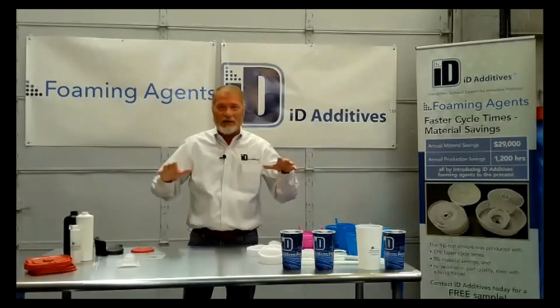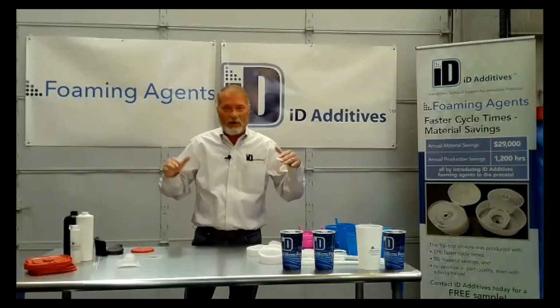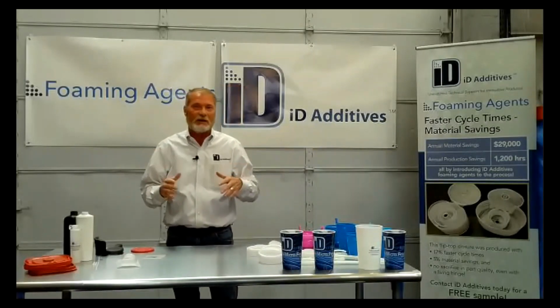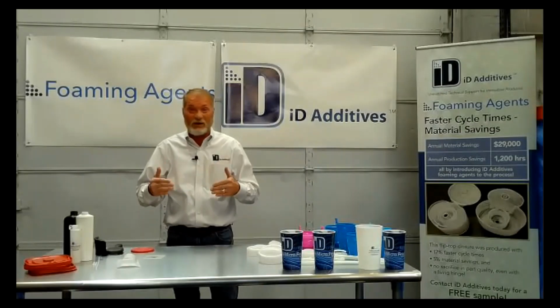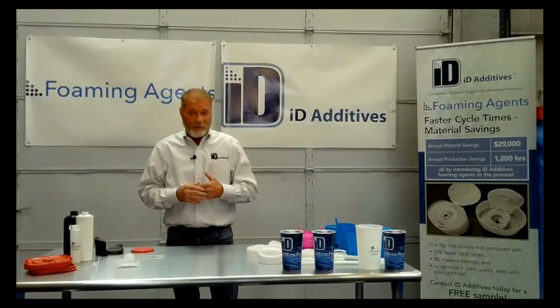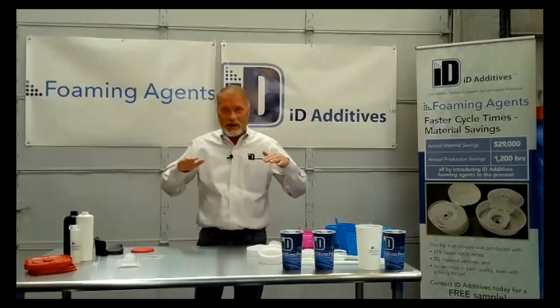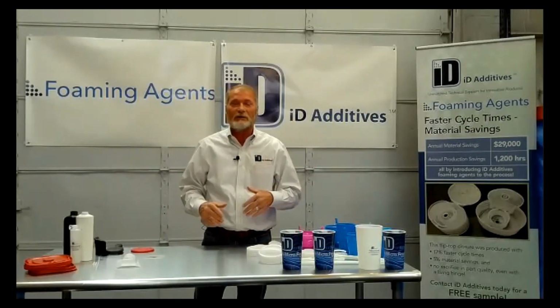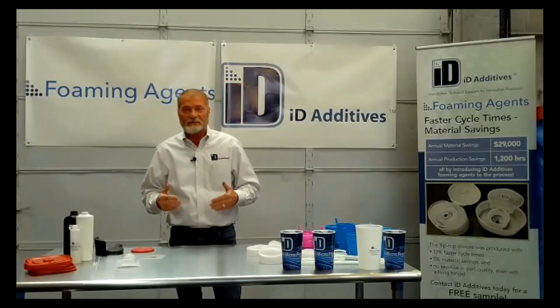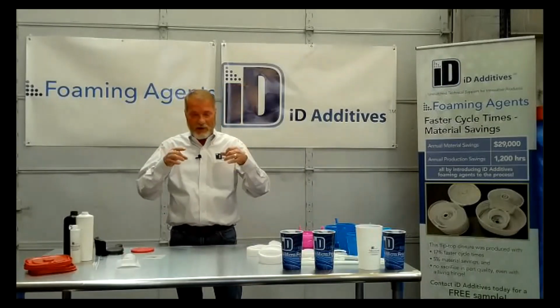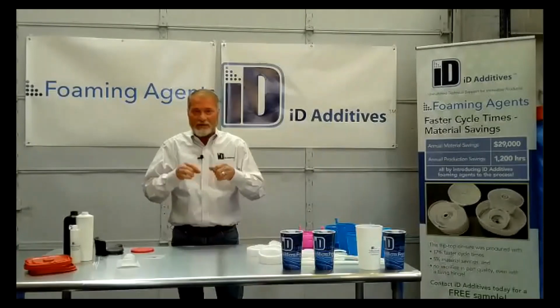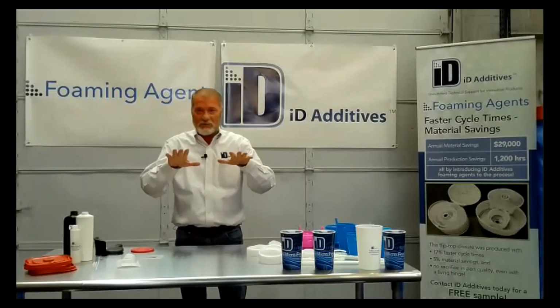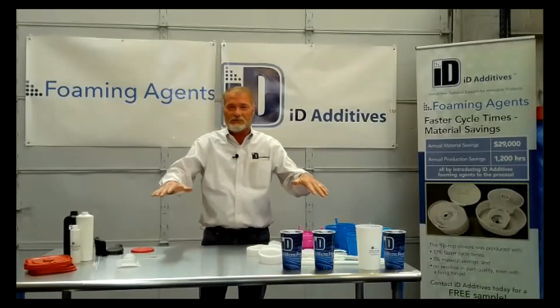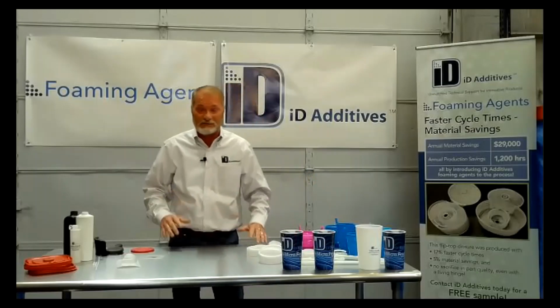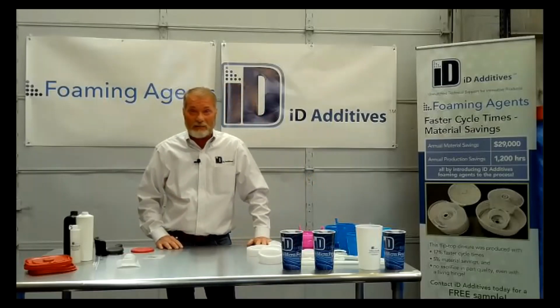It'll look kind of funny how it goes over ribs or goes over corners. I mean, there's a lot of turbulence going on there. So if you just want that real pretty look, nice even splay throughout the part, lower speeds makes that happen. I mean, it can give you right from the gate out just a beautiful splay that flows really nice, and you don't have any turbulence. And because of the low pressure application, you take weight out.